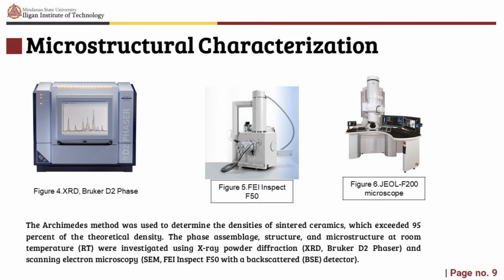For SEM, sintered samples were first ground and then polished to a mirror sheen with wet abrasive paper and diamond paste. Specimens for transmission electron microscopy, or TEM, were prepared by mechanical grinding, polishing, and ion milling. To minimize surface damage to the specimen, a Gatan precision ion polishing system was used to perform the ion milling at liquid nitrogen temperature. The JEOL F200 microscope was utilized for high-resolution transmission electron microscopy and scanning transmission electron microscopy imaging, as well as energy dispersive X-ray spectroscopy research.